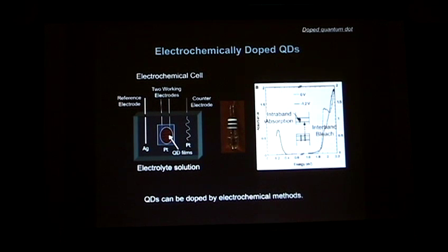But the nanocrystal film is still not very conductive because the nanocrystals are usually intrinsic. So you need to put charges into the conduction band, and then it will be more conductive. It turns out that the conventional back-gate methods are not very successful in nanocrystals, and electrochemical methods turn out to be more successful. And indeed, when you inject electrons by applying an electrochemical potential to your nanocrystal thin films, you are able to see this spectrum change.